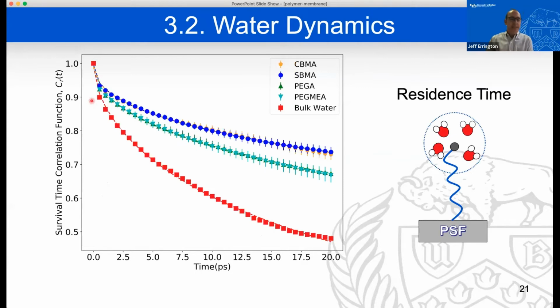Next, we look at the residence time. So here we're capturing the system at time t equals 0, and then we're asking the question, is water still within close proximity to one of the polymer tethers at some time t later? And that information gives us the time correlation function. So here's the time correlation function associated with the different polymer tethers. Here again, you notice that the correlation times associated with the Zwitterionic polymers are higher than those associated with the non-Zwitterionic polymers, again, suggesting lower measures of mobility for water closer to the Zwitterionic polymer tethers.